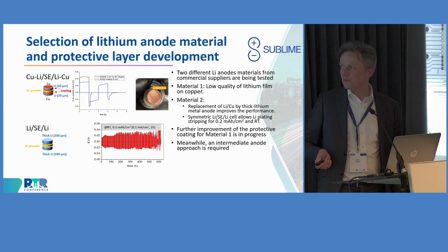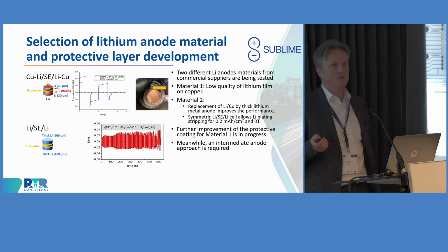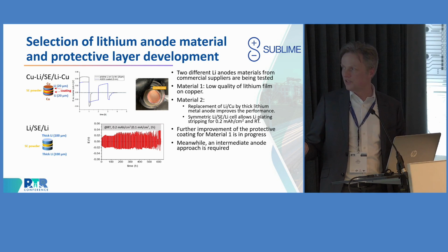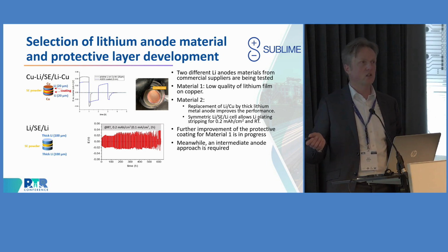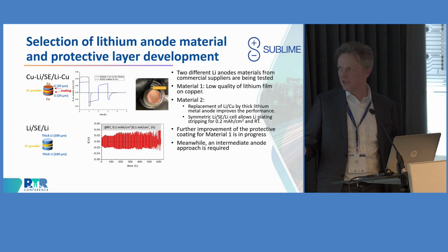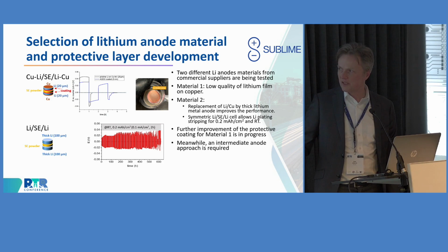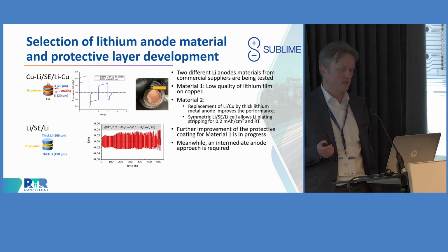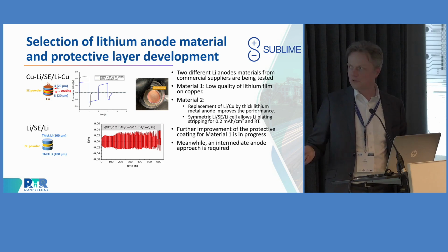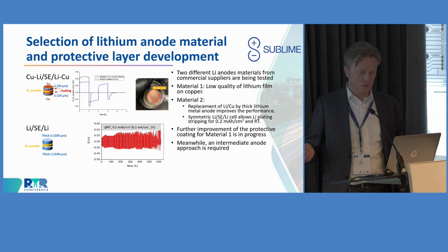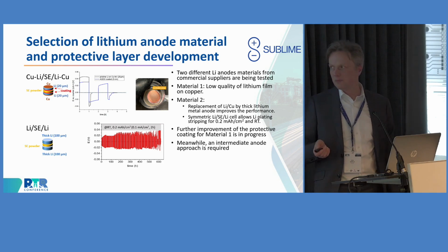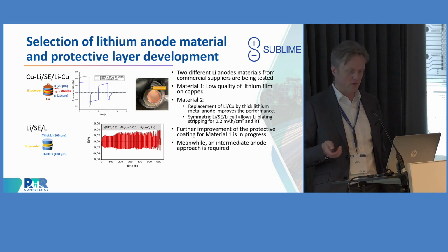very quickly destroying the cell. If we use different kinds of materials with thicker lithium, we see that our approach actually is going to work, so we can cycle quite a lot of times. However, these are thicker lithium anodes, of which we then at the end don't need that much. There is even more material than we need for active material, and that's the reason why we have to develop a little bit more on this technology brick. But we see in principle that our SUBLIME approach works, but of course there is some more optimization needed.